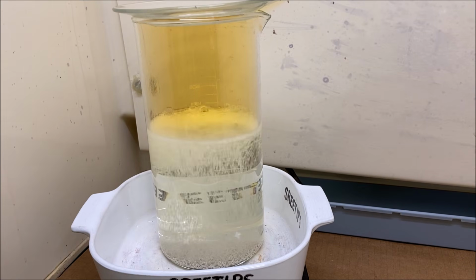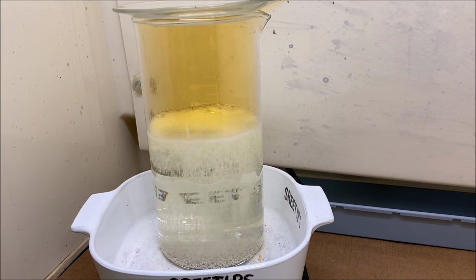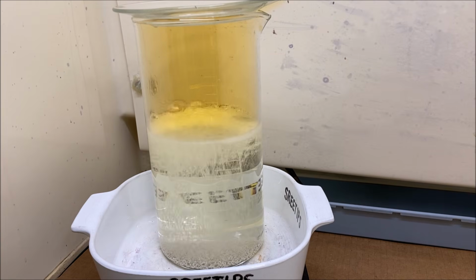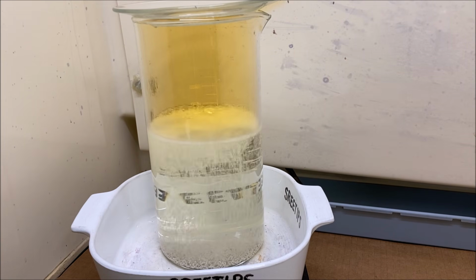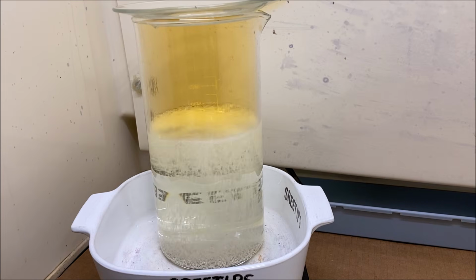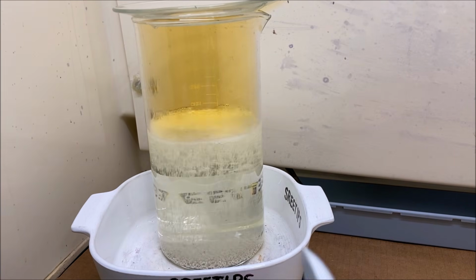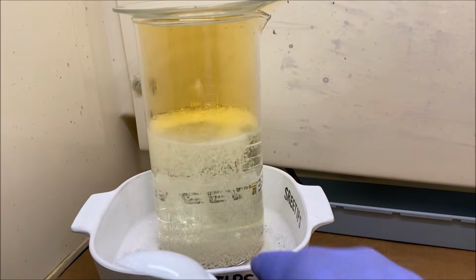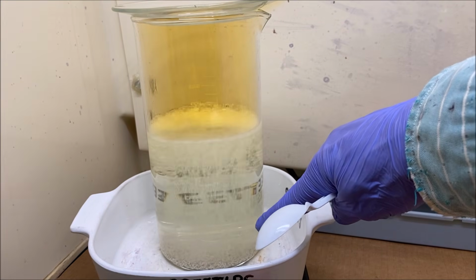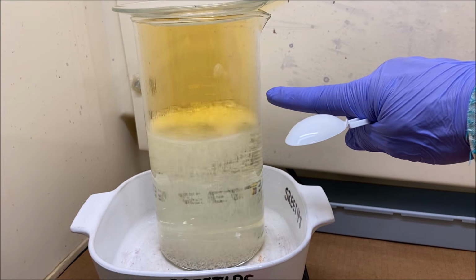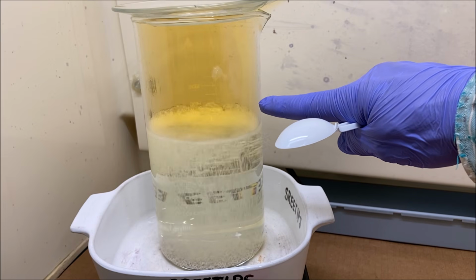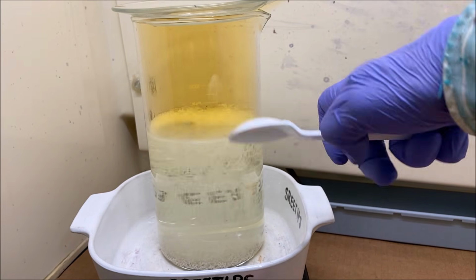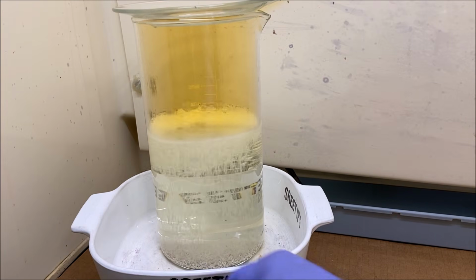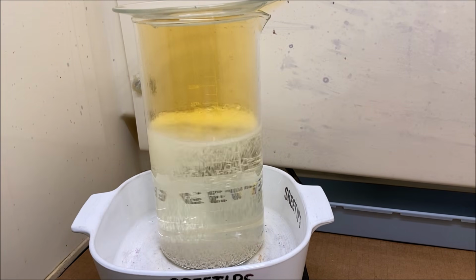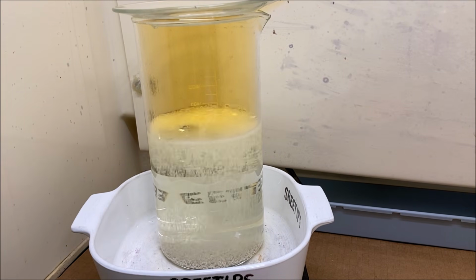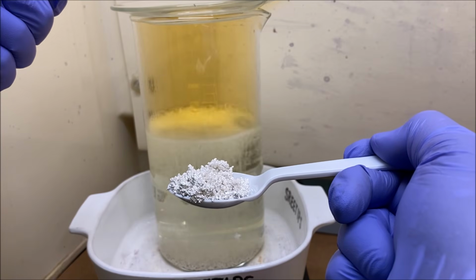This has been boiling now for a little over 2 hours. I added another 200 milliliters of nitric acid and 200 milliliters of water during that dissolve. And so I've got a little bit of silver left down in here. I've still got some fume production going on. I want to boil this until all the fumes are completely gone. And I've got a little bit of silver left down in the bottom of that beaker.